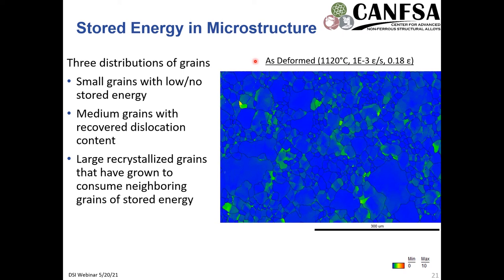But in the as-deformed state, the stored energy distribution within this was quite interesting. We have really three distributions of gamma grains. One is quite small gamma grains with low levels of stored energy distributed throughout here. Secondly, we have medium grains that have a level of recovered dislocation content. I'm calling it recovered because there seem to be dislocation cells, especially near the grain boundaries of the material. And there are some limitations to the GROD technique. Sometimes it misidentifies low angle grain boundaries as being a large amount of dislocations, but I'm going to skip over that for now. And finally, third, we have large recrystallized grains that have grown to consume neighboring grains of stored energy. We have many of these distributed throughout the material, like here, here, and in some instances, some have yet to grow very large.